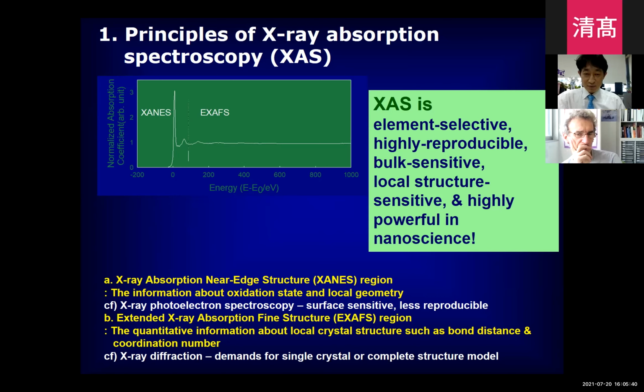And XAS is bulk sensitive, and we can effectively probe the local structure of a specific element. So it is a very powerful tool to characterize nanostructured materials. We can get information about the oxidation state, the local geometry and the chemical bonding nature. It's comparable to XPS, but as I told you, XPS is not so reproducible, although XPS also has its unique merit, high sensitivity to the surface. So if we combine both spectroscopies, we can selectively study the bonding state at the surface and in the bulk.